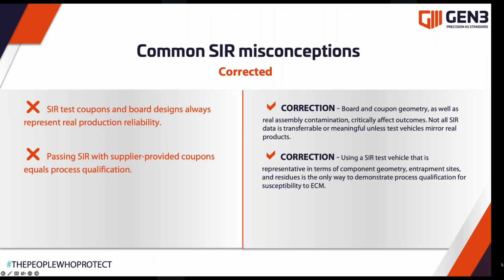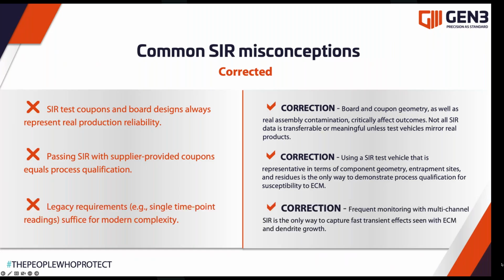Another misconception is that passing SIR with supplier-provided coupons equals process qualification. No, a correction to that would be using a SIR test vehicle that's representative in terms of component geometry, entrapment sites, and residues. That is the only way to demonstrate process qualification for susceptibility to ECM. And then another misconception: legacy requirements can suffice for modern complexity. No, as already highlighted, frequent monitoring with multi-channel SIR is the only way to capture fast transient effects seen with dendritic growth or ECM effects.